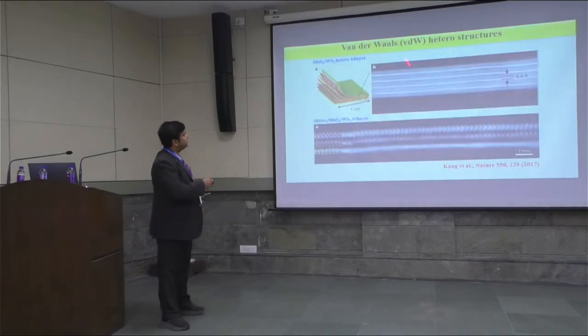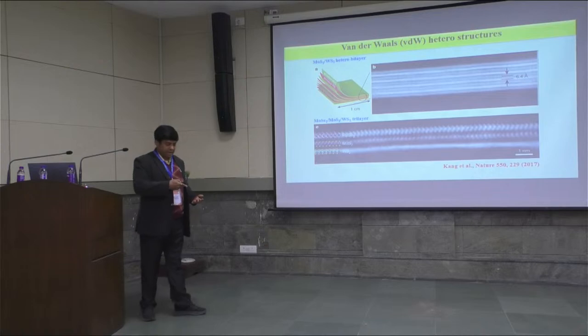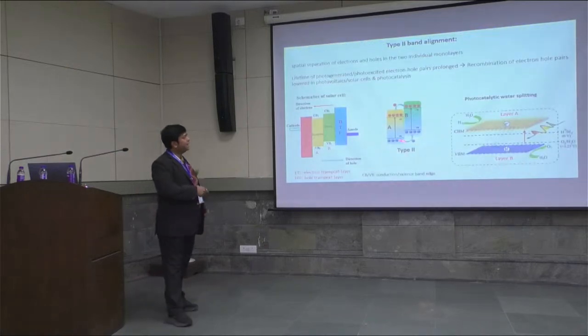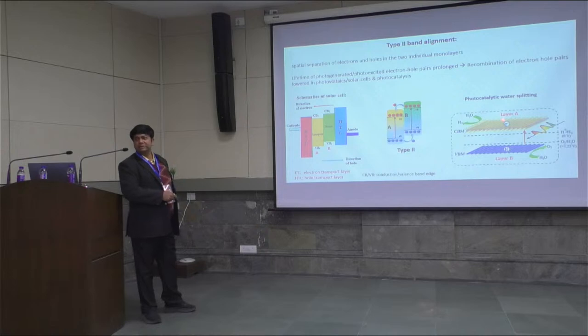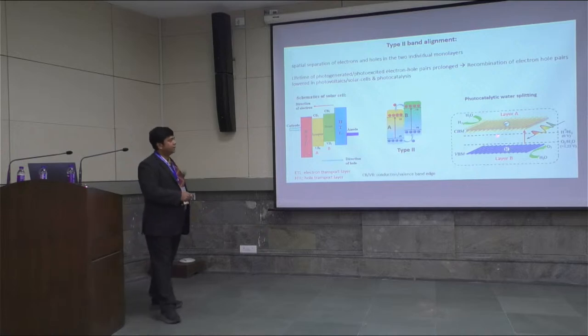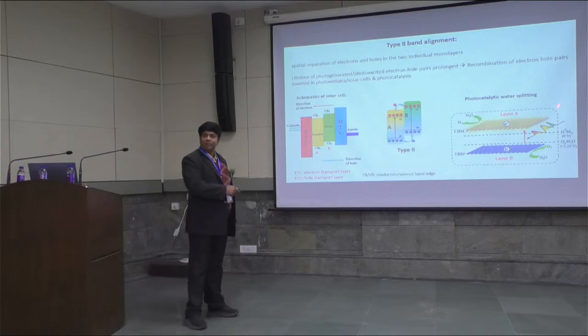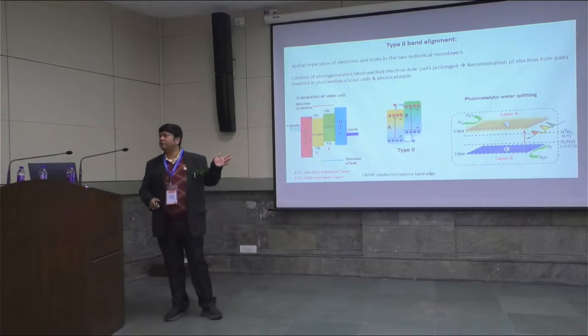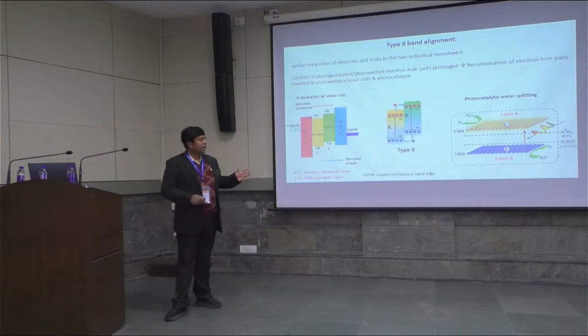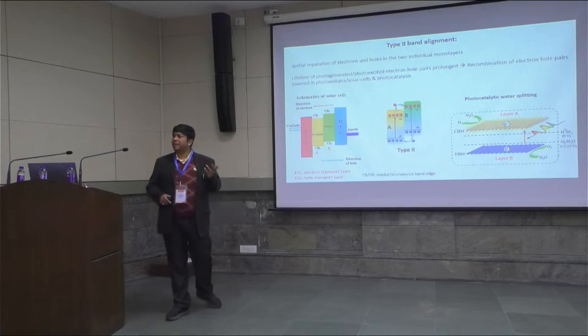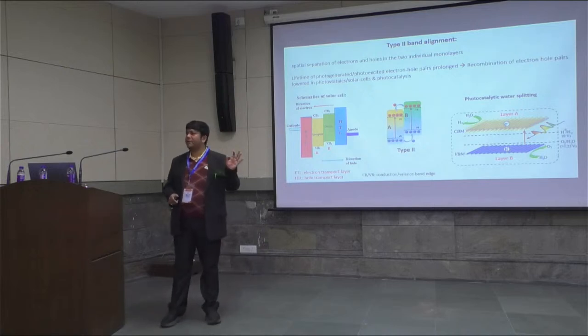So it's time to switch the gear to van der Waals heterostructures. Van der Waals heterostructures have mainly been studied in light harvesting applications, for example, in photovoltaics and in photocatalysis. Because of the type 2 band alignment, the electron hole pairs can be spatially separated in the two individual monolayers. And now, as Professor Pandey mentioned in the morning, interface-driven properties were overlooked.